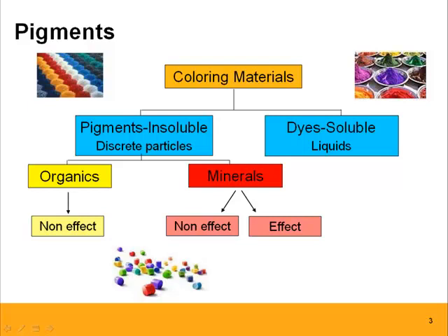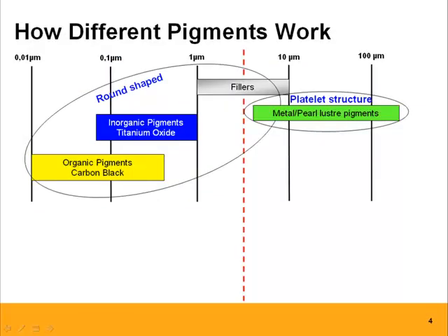So how do different pigments work and what do they do? An important thing that needs to be considered is the size of the pigments. They play a key role in how well we can mix them within the polymer matrix, and what some of the challenges are later on when it comes to color change. The organic and inorganic pigments are in the range of 0.01 micrometer to about 1 micrometer, and they're sort of touching on what typically would be a filler like calcium carbonate or graphite. They're roughly in that same neighborhood.